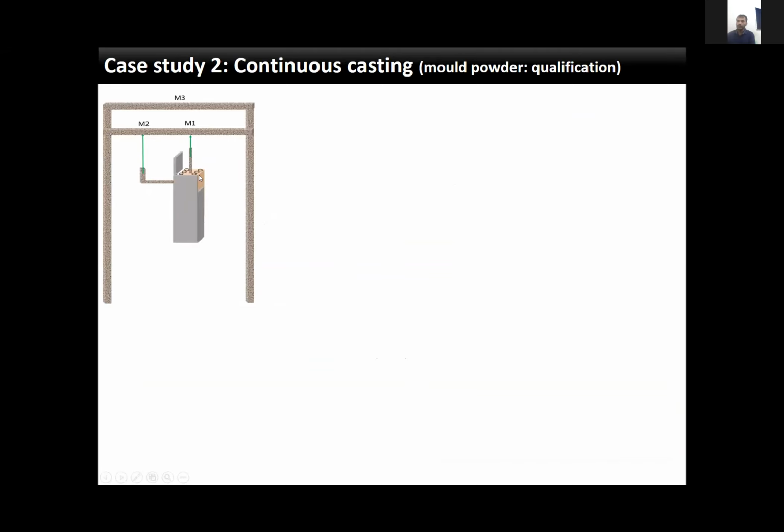You can see the copper mold and the cooling lines are arranged, and this gray color is nothing but a steel shell. All the 3 faces of the copper mold are covered, and one face is partly covered. Okay, and there are different motors. The motor M1 will perform the oscillation of the copper mold with exactly the same oscillation frequency and stroke as in the industry, and the M2 will assist in pulling down this steel shell during the simulation process. That velocity will simulate the casting velocity.